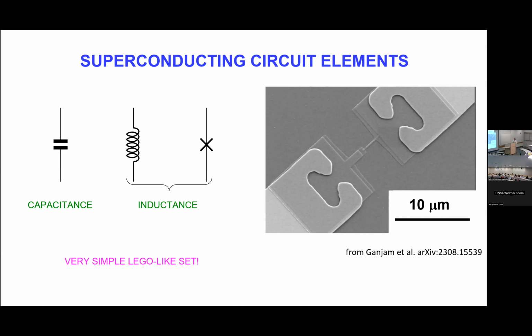And on the other side, if you use refractory metals to make the junction, like niobium, this has been tried, tantalum too, but essentially you cannot deposit with this kind of shadow technique, which means that you have to deposit through a stencil. Essentially, you cook your stencil with the heat that you have to generate to evaporate the metal. So, believe me, people are trying to solve all these problems, but so far, at this point in time, the best junctions are still made in this way.